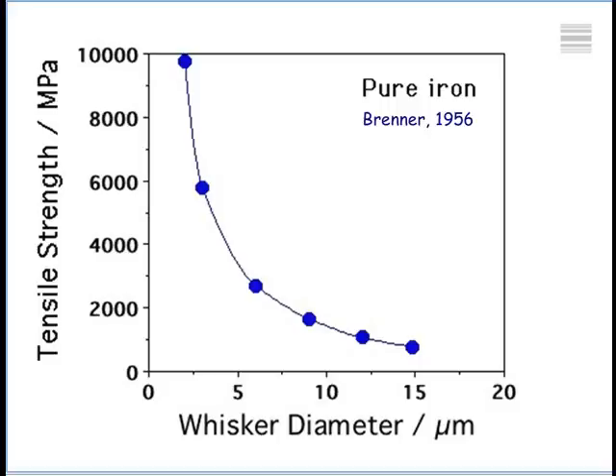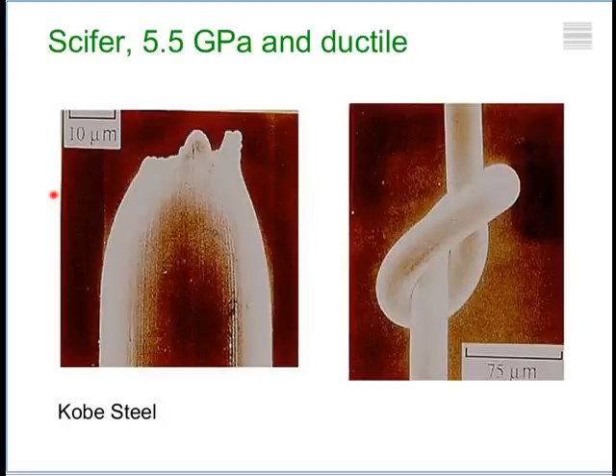Now, I explained to you earlier that we could actually produce strength by introducing a very large number of defects. Okay, so if we deform metal very severely, then the strength will increase. So this is an example of a commercial steel, which is 5.5 gigapascals in strength, and it's produced by severely deforming iron. So just to give you an idea of how much deformation, if you take 50 grams of this material and you stretch it into 2 kilometers, that is the amount of deformation that you need to get to a strength of 5 gigapascals. But notice that it's very ductile, okay? That means it can deform. If you take a carbon fiber, which has a strength of 3 gigapascals, it has almost zero ductility. You cannot tie a knot with a carbon fiber.